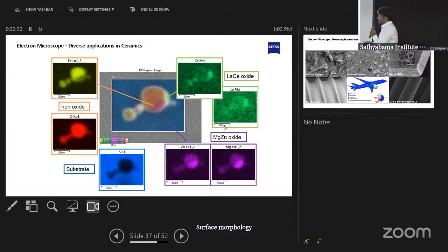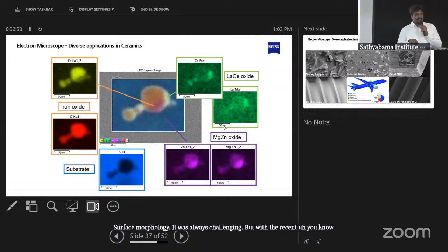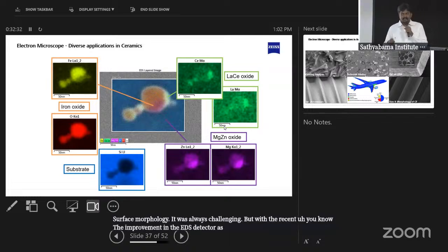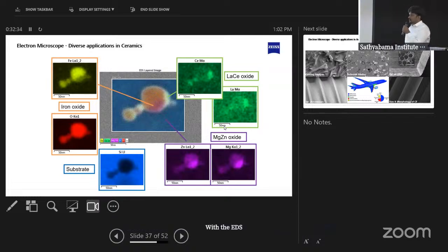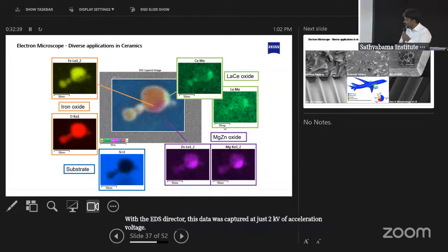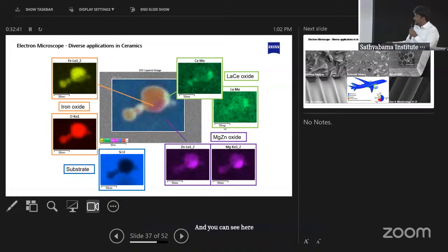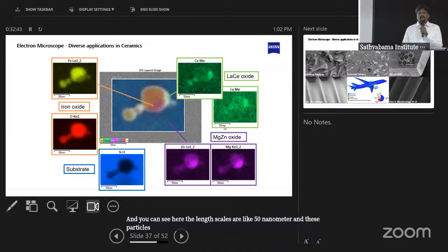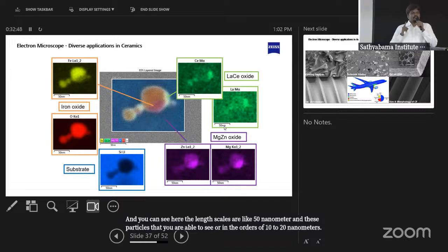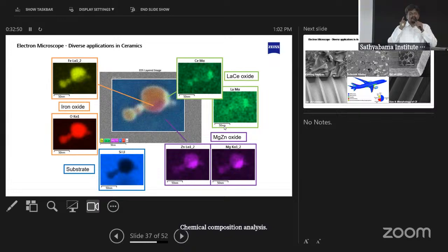So it was always challenging, but with the recent improvement in the EDS detector as well, not necessarily only imaging, this data was captured at just 2 kV of acceleration voltage. And you can see here the length scales are like 50 nanometers, and the particles that you're able to see are in the order of 10 to 20 nanometers. So chemical composition analysis, even on a non-conducting sample, is possible right now. Electrically non-conducting, which was not possible a decade back, right? All right.